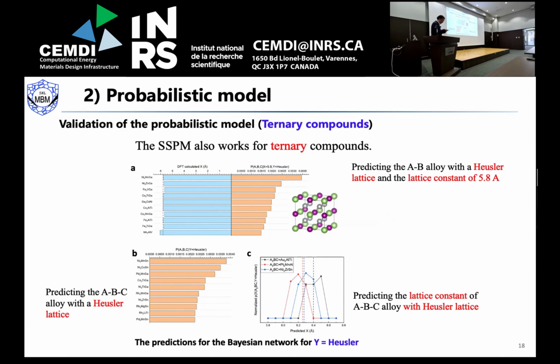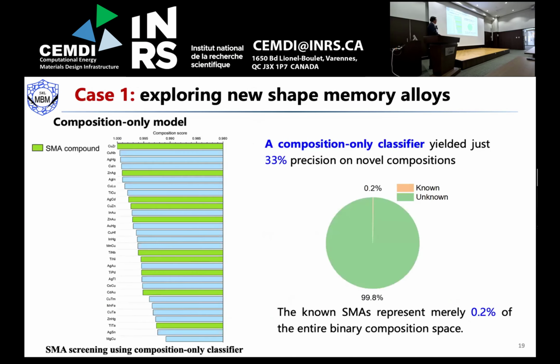Then we can use our model to do the predictions. And these are the top 30 alloys predicted by our method. The green ones are real. After we check with our knowledge, we found that only one third are real shape memory alloys. Two thirds are not shape memory alloys. That means the accuracy is only one third.